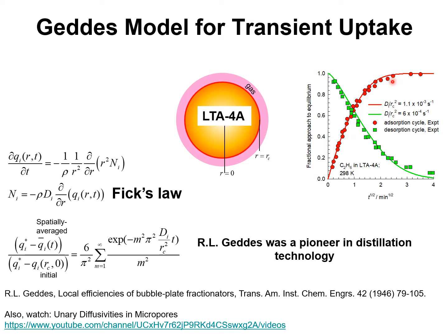We note that the desorption cycle is slower than the adsorption cycle, and the reasons for this asymmetry in the adsorption and desorption cycles are due to thermodynamic corrections that come into play. For further details, I refer you to my video presentation on thermodynamic correction factors and diffusivities in micropores. The right-hand side of the analytic solution requires at least about 20 to 30 terms to get an accurate representation of the spatially averaged loadings within the particle.